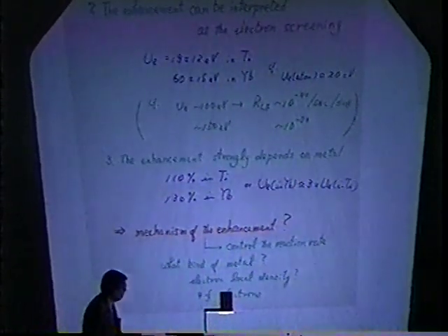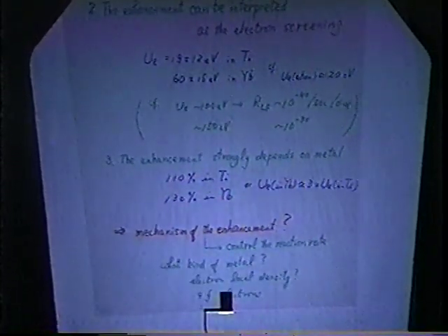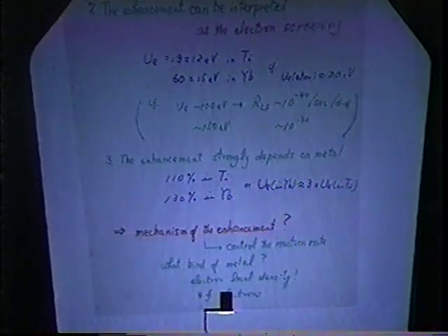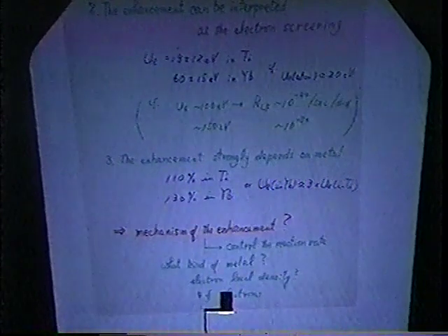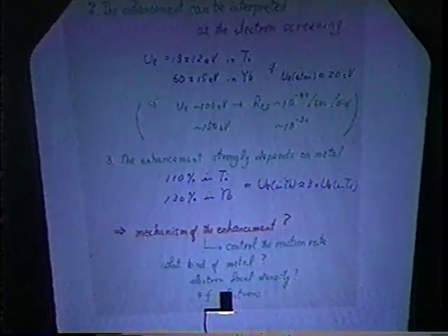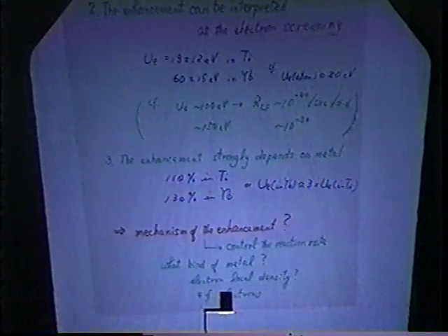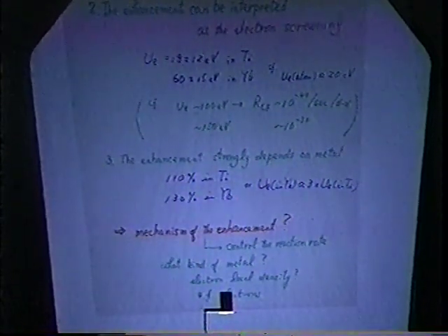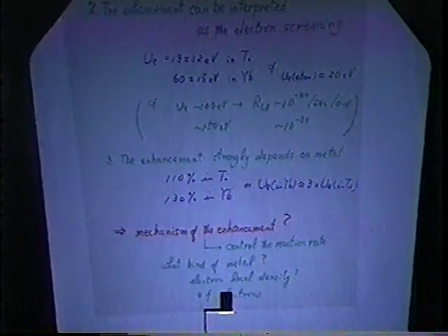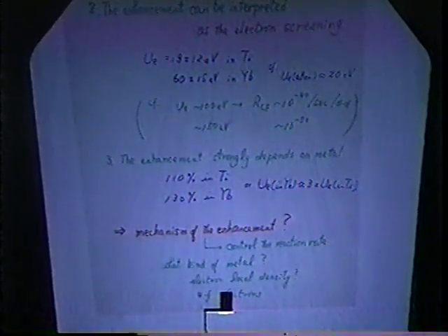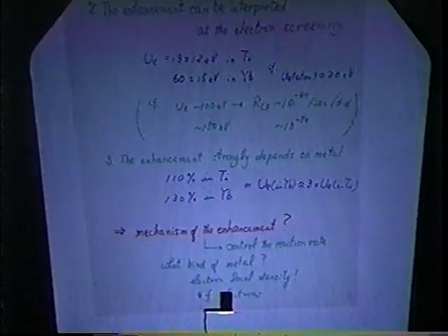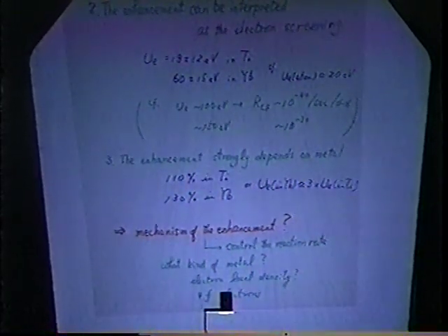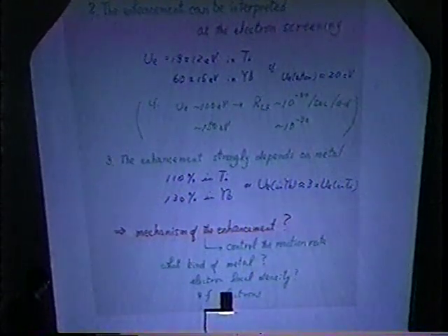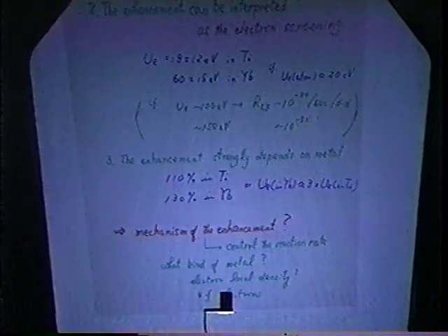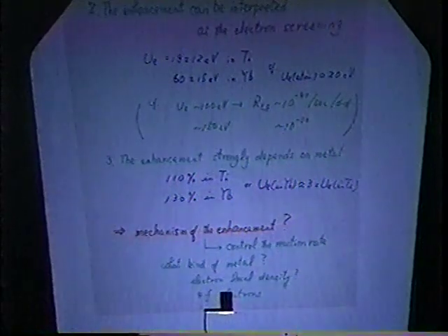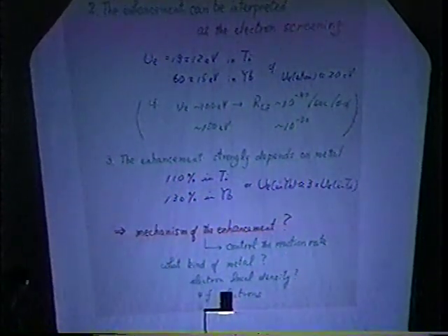But also, I think it's an important point. The enhancement strongly depends on the metal. I mean, that depends on the environment of the nuclear reaction itself. So our result tells us that if we use titanium, there is 110% enhancement, but if we change the metal, the enhancement changes. And that's why we should study the mechanism of this enhancement for very low energy nuclear reactions.